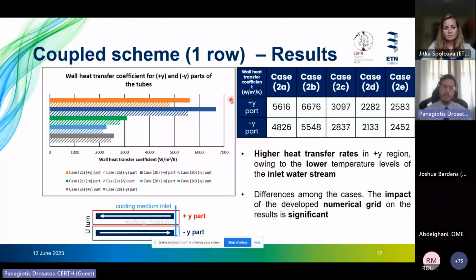And here you can see the absolute values regarding the wall heat transfer coefficient for both parts of the tubes before and after the U-turn formation. Of course, the highest absolute wall heat transfer coefficient values are developed in the first part of the tube formation, due to the reasons that we have already explained. However, the differences among the cases are significant, so we can conclude that the impact of the numerical grid density on the derived results is significant. Some lighter differences can be spotted among the last three cases, which all are characterized by high grid densities.